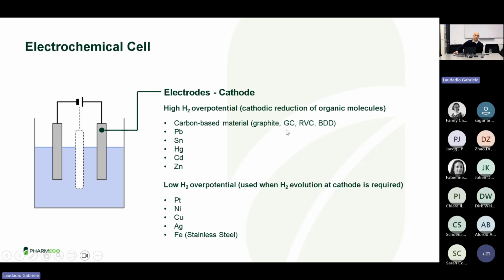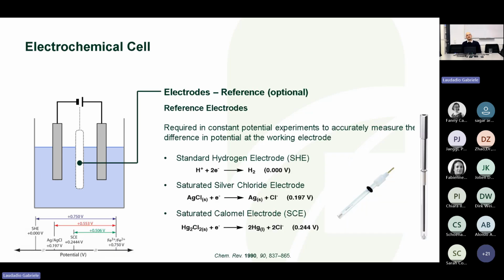In case we are, for example, more focusing on the oxidation, we can use the evolution of hydrogen as the counterpart of the reaction. And in that case, we can use platinum, nickel, or, for example, stainless steel. Another electrode that can be used in this kind of setup is the reference electrode. Reference electrodes are usually optional because they are commonly used in potentiostatic mode, so at constant potential. Generally speaking, nowadays we can purchase them standalone, and they can just be submerged into the reaction media.